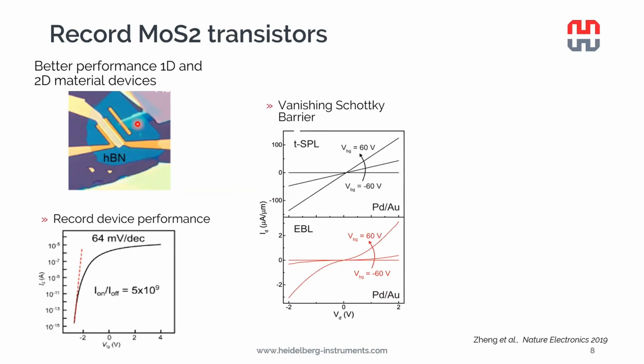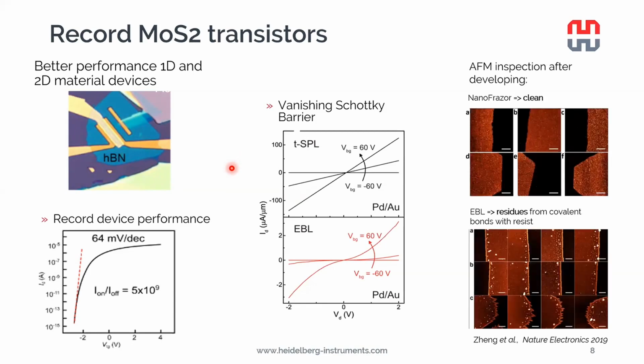The device itself looks like this: source and drain, and then there's a hexagonal boron nitride top gate dielectric, and the top gate on top. All of the electrodes were patterned using a NanoFrazor and the bilayer lift-off process.